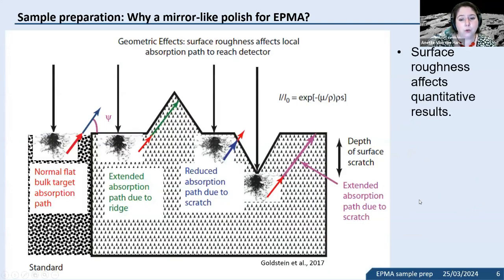In my third talk I discuss the specifics of matrix corrections, but again, absorption is a big part of it. The depth at which our X-rays are generated has an important effect, and we usually compare the intensities that we get on standards. If the standards are well polished, which they should be, any difference in surface roughness can lead to higher or lower intensities. For example, X-rays are emitted throughout and need to go to a certain spectrometer or detector. If they have to travel through a relative topographic high, there's a longer absorption path, so our intensities might drop because they travel through more material, versus if there are a lot of depressions from scratches or something,